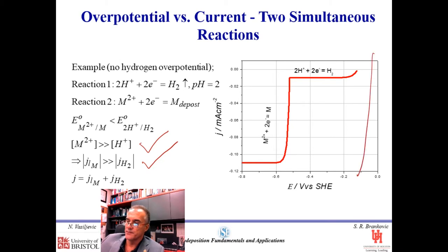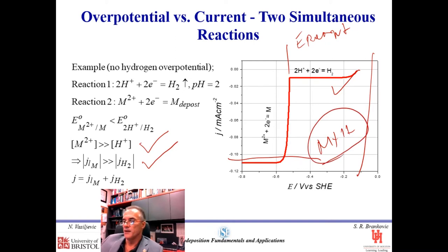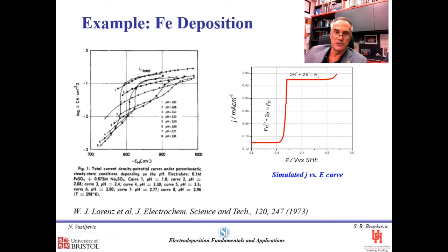And in that case, the typical outlook of the current density or potential relation looks like this, where we have two plateaus. The first one is related to the limiting current density region for hydrogen evolution. Then when we exceed the metal reversible potential, we start to see another increase in the current, and then another plateau, which is basically the metal plus hydrogen deposition limiting current. And this is shown for iron deposition, which has a hydrogen co-deposition current. And you can see for different pH, the shape of the curve starts to look close to what we just described. Keep in mind that here the abscissa is a logarithm of the current.